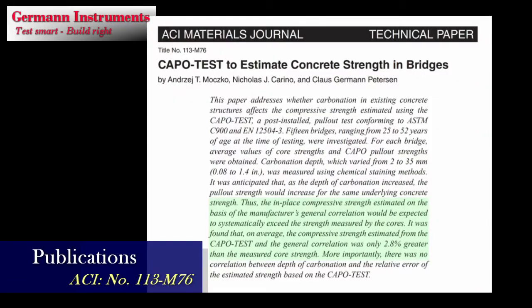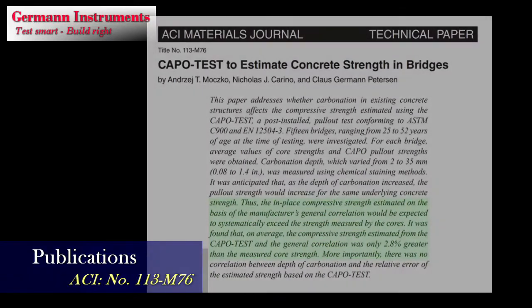For testing on site, the ACI Materials Journal, Technical Paper No. 113M76, reports from testing of 15 bridges, 25 to 52 years of age, ranging in strength from 15 megapascals to 50 megapascals. On average, the compressive strength estimated from the CAPO-Test was 2.8% greater than the measured core strength when the manufacturer's general correlation is followed. This is despite the concrete tested was carbonated up to a 35 mm depth.